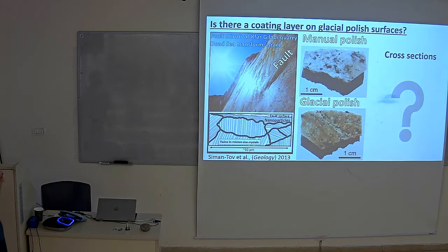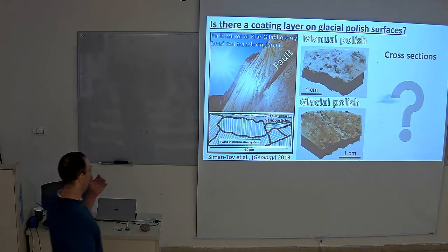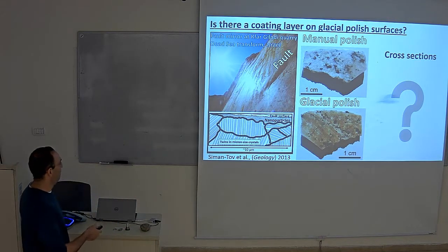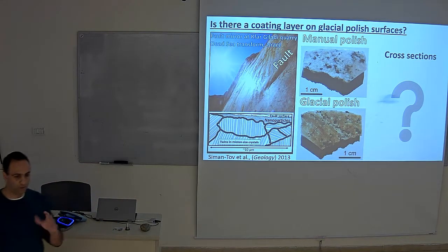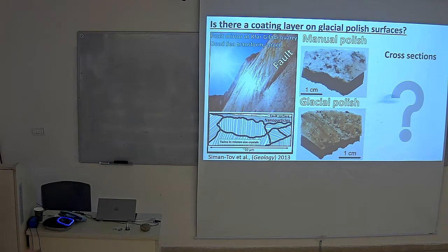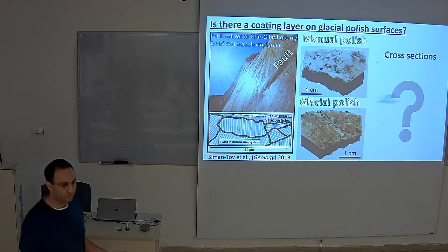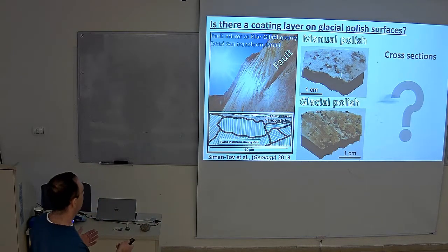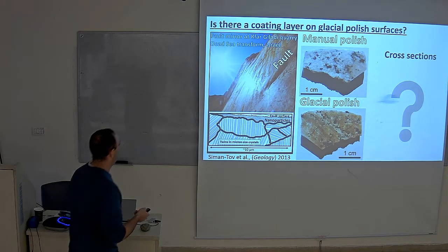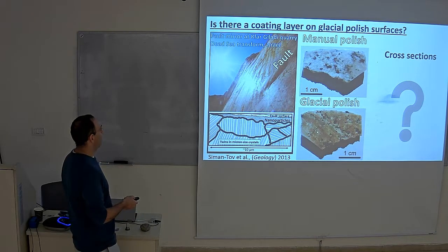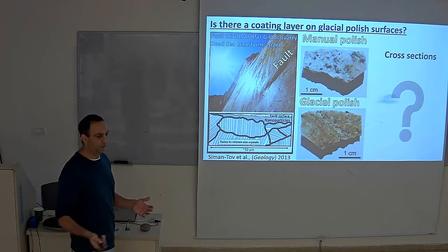However, when we look at the small scales, we see that the polished surface is actually formed by a coating layer, a micron-sized thick layer that is on top of the surface. It's made of amorphous material and nanoparticles, and it's formed during fault slip. And the question is if it's the same for any polish. If, for example, we take a manually polished sample and a glacial polish, will both show a coating layer, and is that the reason they are shiny?